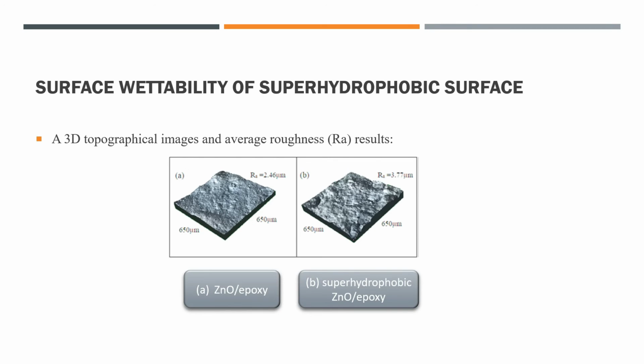The average roughness of the zinc oxide epoxy surface is 2.46 micrometers as shown, which is mostly due to the coarse structures generated on its surface. Meanwhile, the average surface roughness of the superhydrophobic zinc oxide epoxy has increased to 3.77 micrometers with the addition of stearic acid to the coating, owing to the production of richer topography generated by stearic acid modification. As a result of the air trapped within the rough surface interspace, the surface can achieve superhydrophobicity.